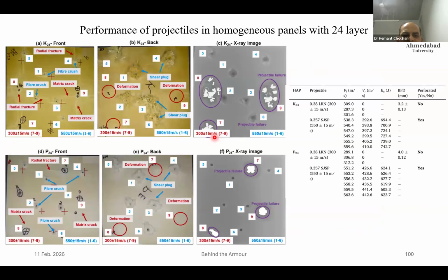So these studies gave us a bit of confidence, and then we thought of having a 24 layer system based on our past studies. Still we found the same, that 550 meters per second is beyond discussion and it will perforate. However, for the 300 meters per second bullet, that is 0.38 LRN, the BFD came down significantly. The projectile was damaged significantly because of the higher number of layers, as demonstrated in this X-ray image, and these petals remain the same for the PE side or the pure PE.